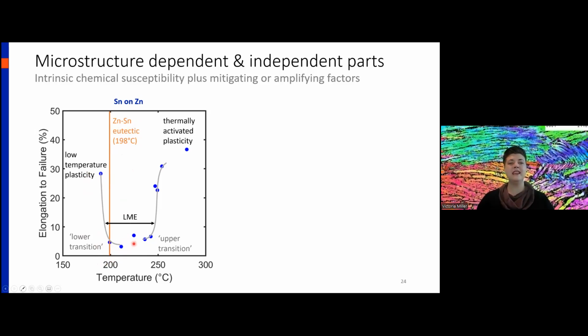But then as we continue to increase the temperature, thermally activated plasticity starts occurring. So we get ductile behavior again, and we start getting more elongation to failure. So this is the way to think about this: there's an intrinsic chemical susceptibility to liquid metal embrittlement. That's why you do get embrittlement. But then there are mitigating and amplifying factors, so things like thermally activated plasticity.